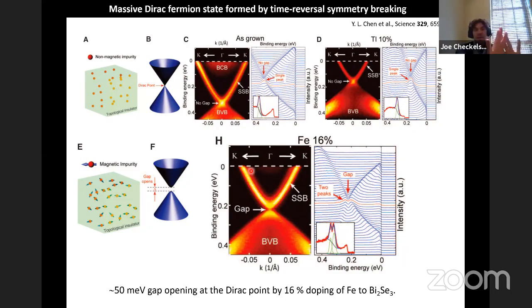So if my recollection of this paper is right, these were grown by a bulk method. So really the whole crystal has iron in it. Therefore, the iron was everywhere. There's nothing you can do to get rid of it. But you can definitely do the experiment you're talking about, especially using these modern techniques in photoemission where you spray magnetic ions on one surface and not the other. And there was a really long theoretical debate about whether or not you could physically imagine disconnecting those surfaces.